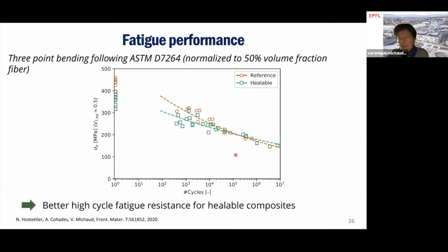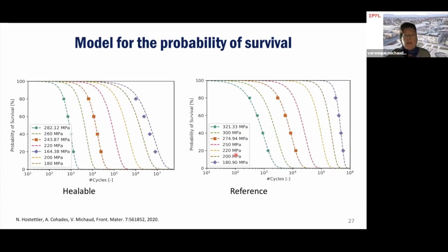Now, what is interesting is what happens if we do a healing treatment. For this, we had to find when to do the healing treatment, and we developed a model for the probability of survival as a function of number of cycles for the healable and the reference composite. And we see, for example, if I put myself here at 243.87 megapascal, at this number of cycles, I have about 40% chance of survival. And then as I increase the number of cycles, the chance of survival decreases. So we decided to put ourselves at 90% chance of survival when we do the healing. Which means that we take the material, we do the number of cycles that we need, then we stop, and we put it in the oven for half an hour at 150 degrees, and then we test again.